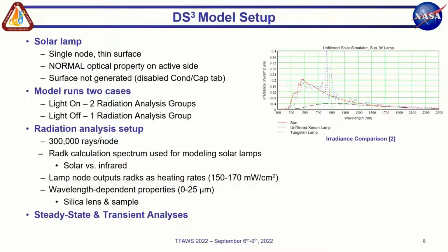And then for other parameters, 300,000 rays per node was used. Solar versus infrared was used in setting up the solar lamp. So solar was selected in the rad group that included the lamp. Infrared was in the one that did not. And for wavelength dependent properties, we went from 0 to 25 microns, mainly because that was all the data we had for the sample as far as optical properties. And mostly steady state was run, but there's also one transient analysis that I'll discuss later on.